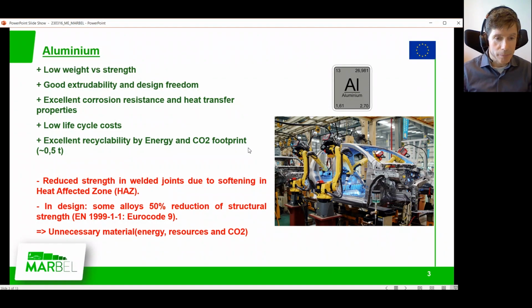So it is beneficial in most of the cases, especially when recycled, but it has some disadvantages when it comes to manufacturing. It has a challenge when it comes to welding. In the area close to the weld, called the heat affected zone, you have reduced strength. And in design of some alloys, most of the high strength alloys that we use, there is up to 50% reduction of the structural strength you can use.